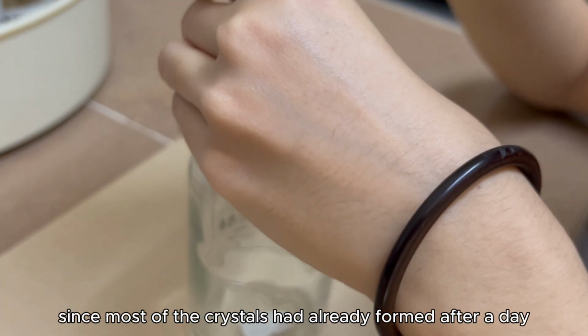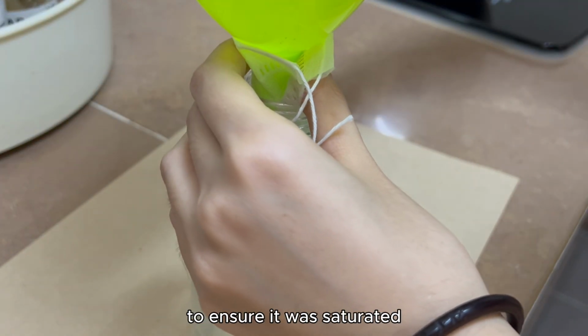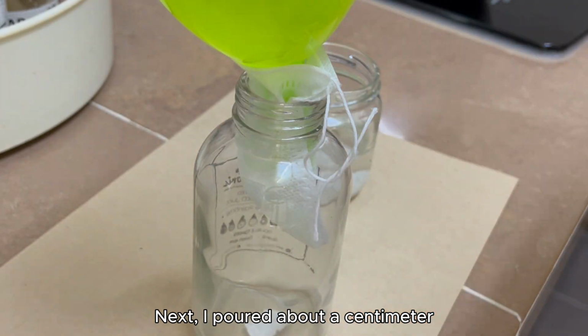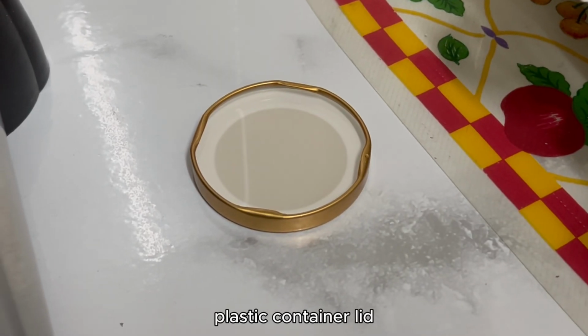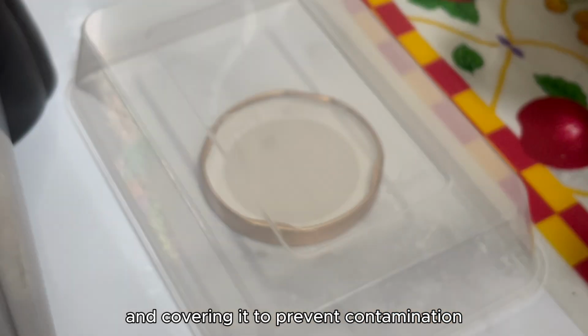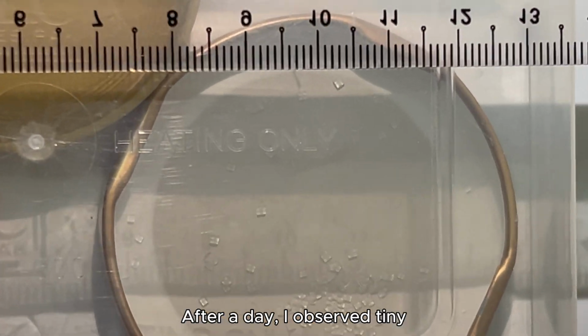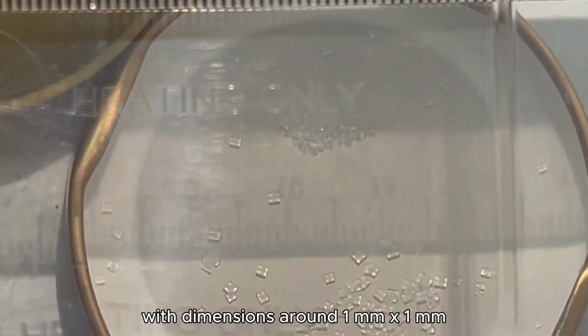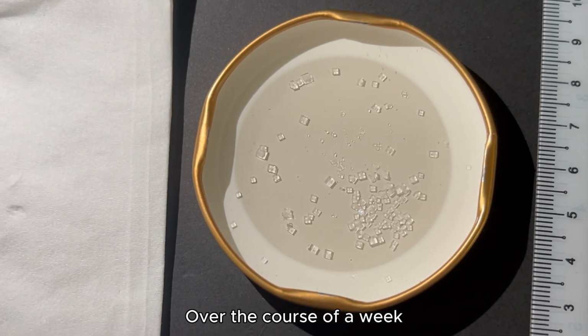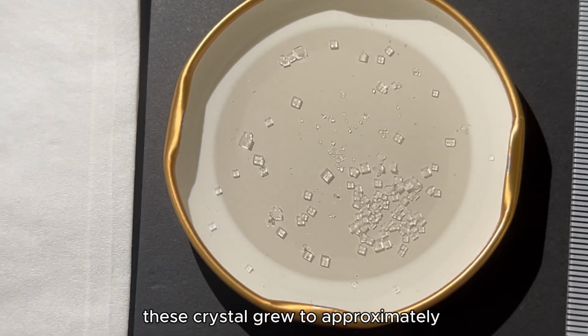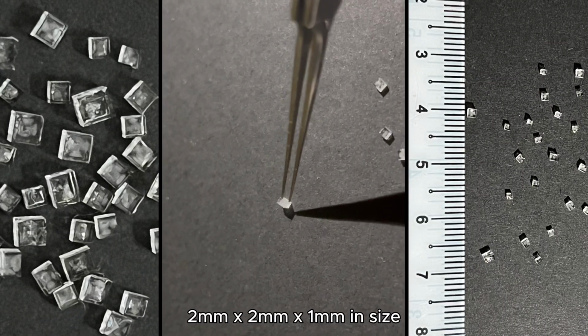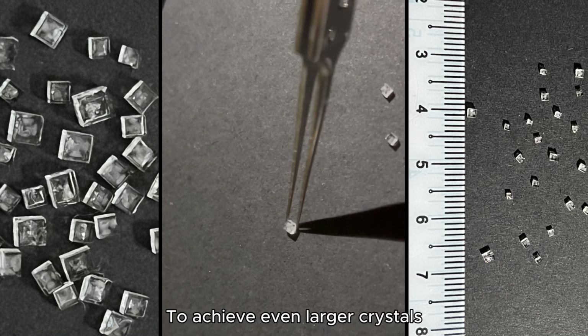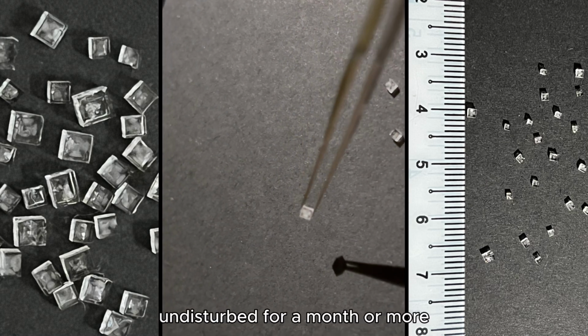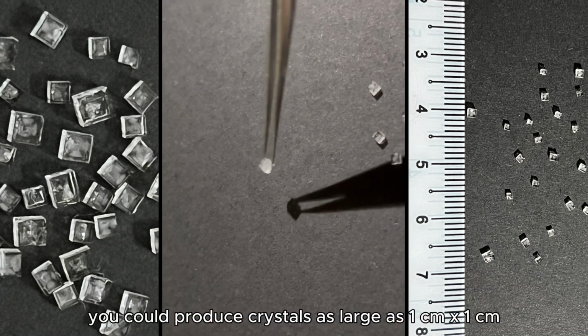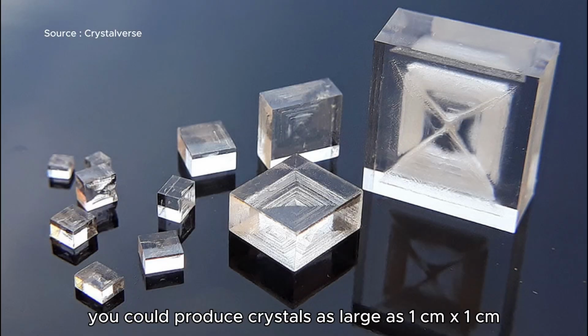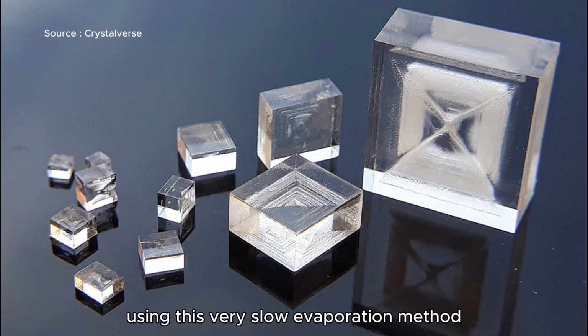Since most of the crystals had already formed after a day, I filtered the solution again to ensure it was saturated. Next, I poured about a centimeter-thick layer of the solution into a flat plastic container lid and covered it to prevent contamination. After a day, I observed tiny transparent cubic crystals with dimensions around 1 mm x 1 mm. Over the course of a week, these crystals grew to approximately 2 mm x 2 mm x 1 mm in size. To achieve even larger crystals, the solution would need to be left undisturbed for a month or more. By then, you could produce crystals as large as 1 cm x 1 cm using this very slow evaporation method.